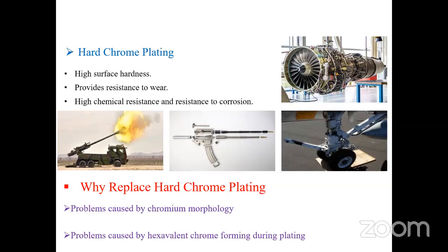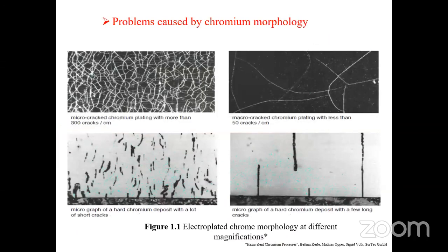But there are two main reasons to replace hard chrome plating. The first, problem caused by chromium morphology, and the second, problem caused by hexavalent chrome forming during plating. Problem caused by chromium morphology. The micro and macro crack rough surface of hard chrome plating is shown at different magnification in the figure. These cracks affect not only the chrome plating but also the coated part.